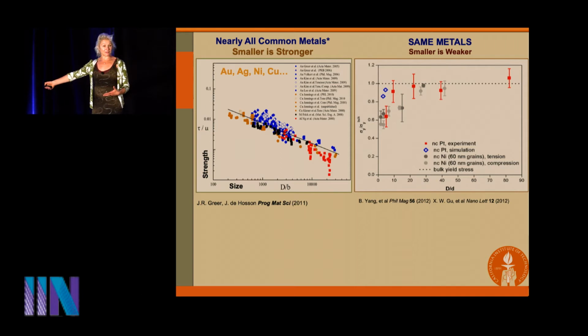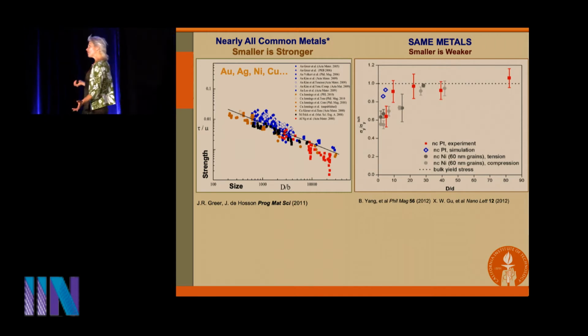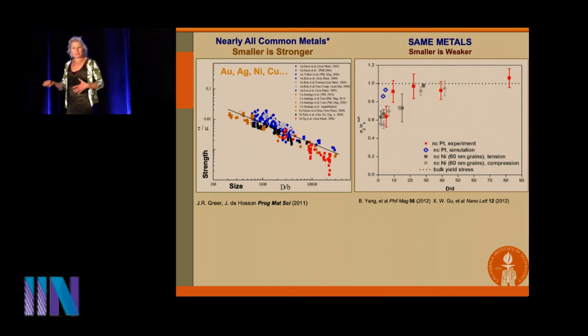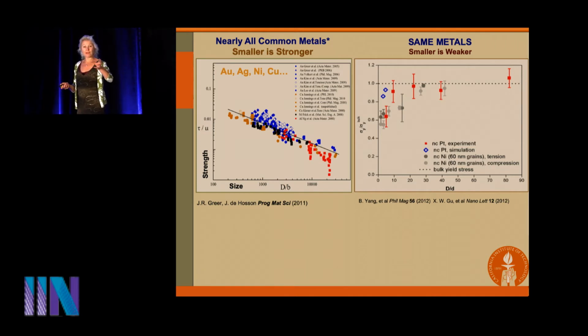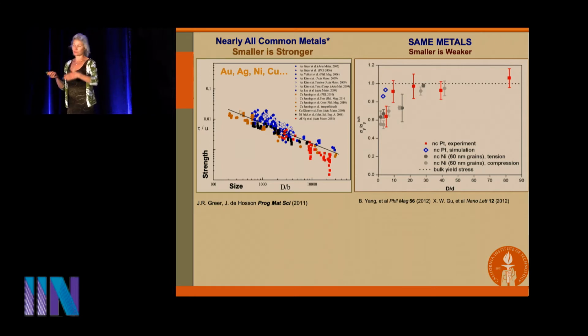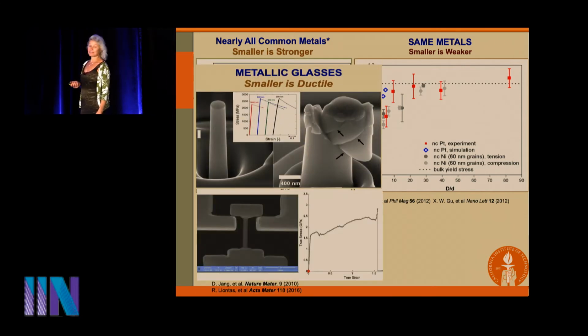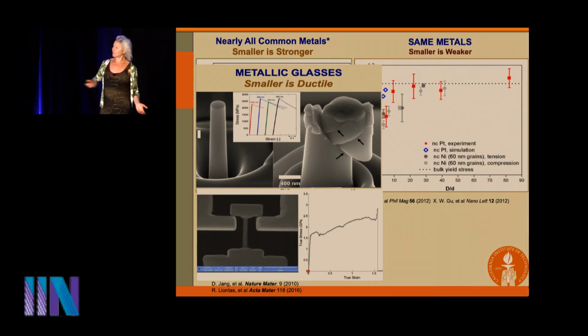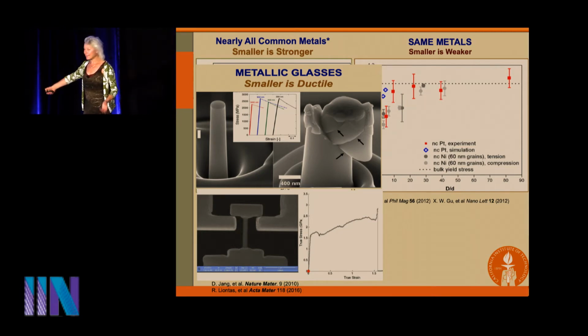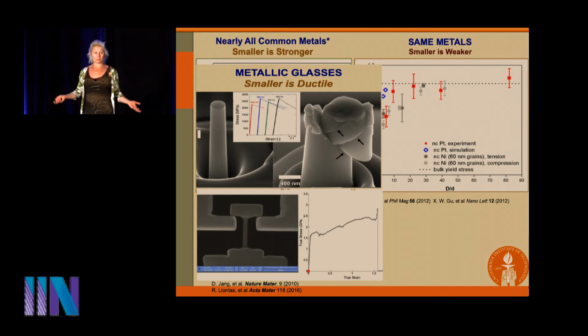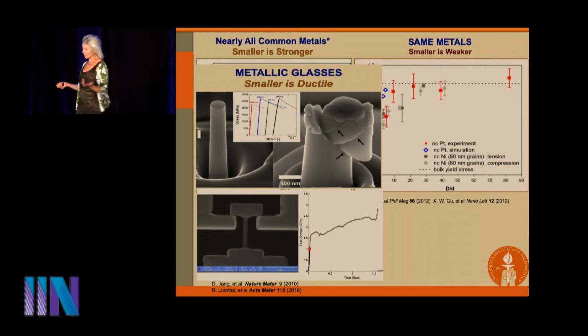This is a more modest size effect. It's not a log-log plot, but nevertheless, the smaller dimensions now give rise to weaker materials. So now you're starting to think, oh, it's the same metals. But now we have this tunability in strength by virtue of size reduction in a different atomic-level microstructure. Now, the size effect is even more powerful than that. If you look at a glass, this is a glass rod. It's about 150 nanometers in diameter, and we're going to pull at it. Now, of course, we all know that's not possible. Nobody at room temperature is able to just pull on a glass rod and get anything useful out of this.